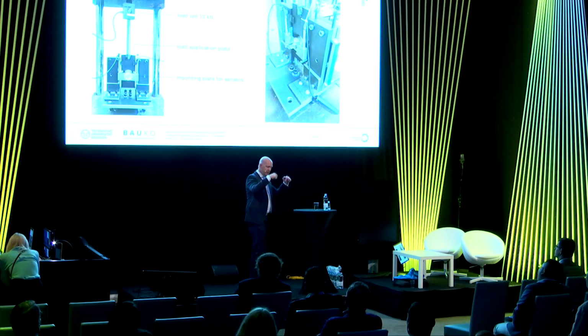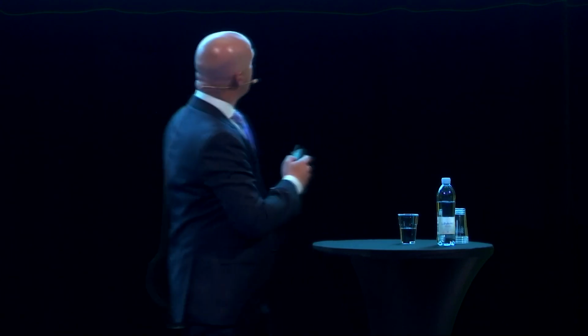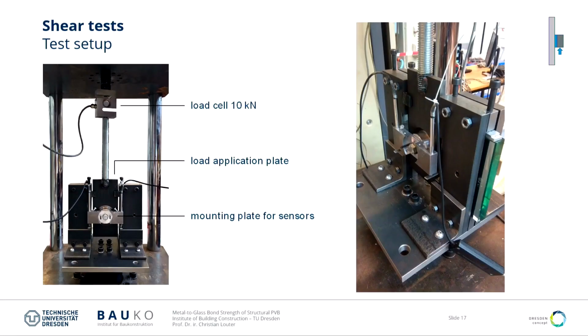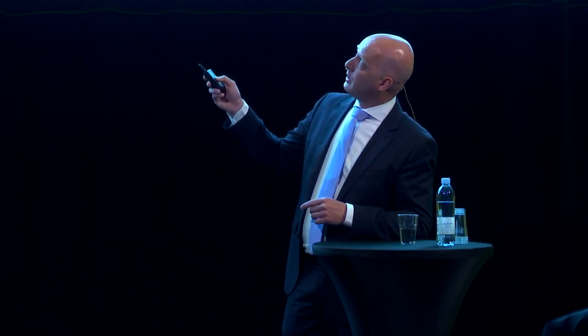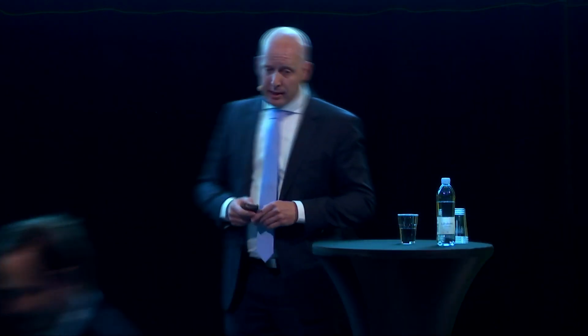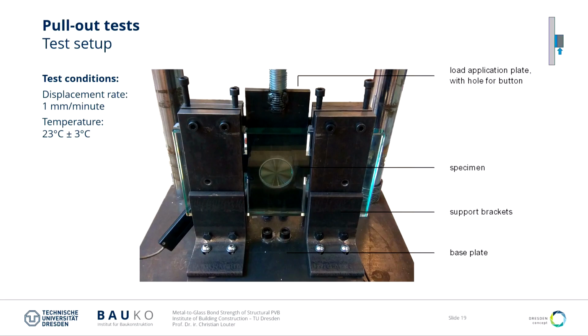At the same time, we are measuring the deformation of this steel button by these LVDTs that measure the relative displacement to the glass. So the local displacement of the button relative to the glass. We record the load at this side with a load cell of about 10 kilonewton. So the tensile force is exerted here, and then it's measured there. This is the same setup, but from the other side. So now we look through the glass. You can see the metal button is laminated there, inserted there. It's blocked over there, and this piece will move upwards to shear the specimen.